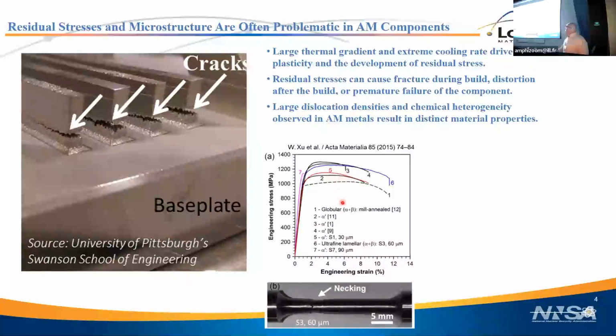This is a comparison of additive Ti6-4 to standard wrought material, which is the dashed line. You see that in every case, and it varies depending on how you do it, but in every case, the additive Ti6-4 has a higher yield strength, higher flow strength, and less ductility. That's because the microstructure of additively manufactured Ti6-4 is different. So that's just the nature of the beast with additive. It's going to create microstructures that are different than we're used to.